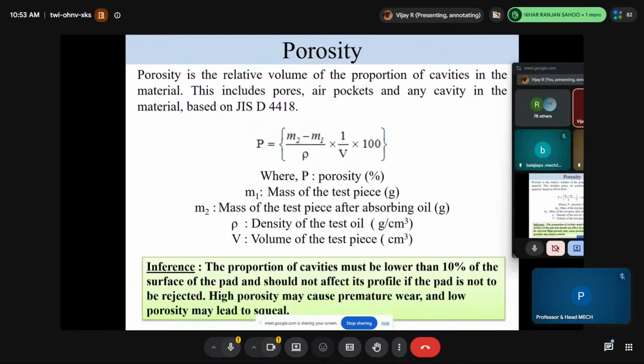Porosity, kindly know it is not internal porosity, it is surface porosity. People may say, sir, porosity is a void, and a void means the material is failing. Yes, the material is failing. But I am saying surface porosity, not only internal porosity. Surface porosity is measured by this study, JIS D 4418, while internal porosity has a tapping method and some other NDT method. If that does not pass, the pad is thrown out without any mercy. So these studies will be done.